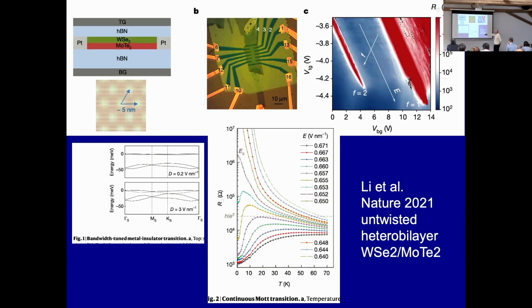This is a little band structure cartoon, well, actually a calculation, that shows how by changing the displacement field, the difference between the top and bottom gate, you can actually change the band structure. You see here, you can get a very narrow bandwidth band, hence making it very strongly correlated. And here you can get a somewhat higher bandwidth and so on and so forth.